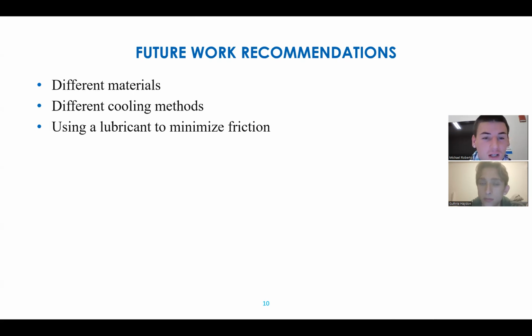And also we could use a lubricant to minimize friction, as when you are using the Rockwell B and C hardness testing method, especially Rockwell C, when you use the pointed diamond tip and it cuts into the materials, there is friction between the diamond tip and the material, which can change up the data a little bit and skew the data as well.